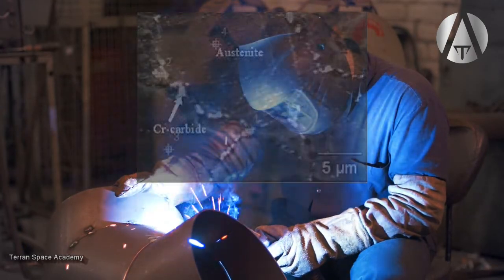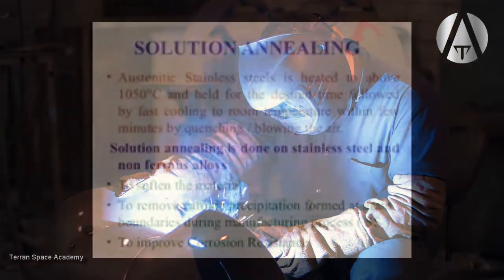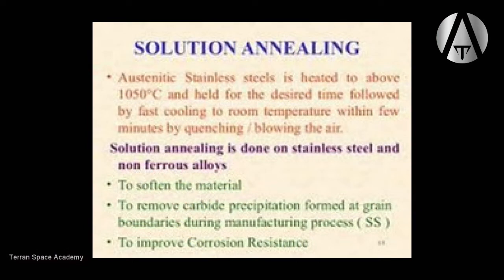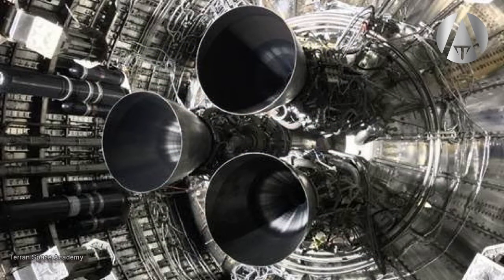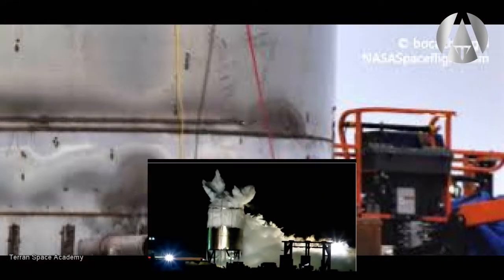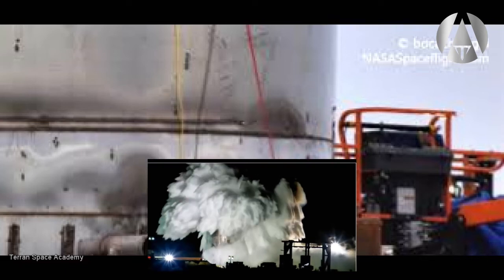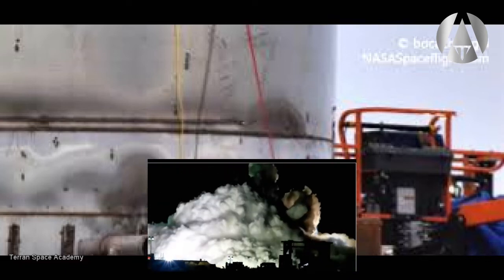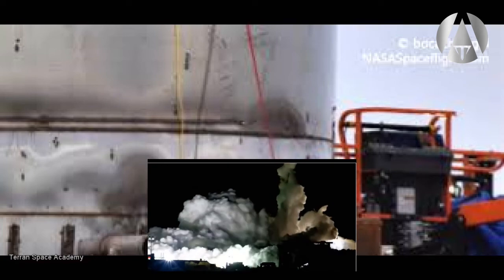What is the solution? SpaceX uses an annealing process to increase the corrosion resistance of the welded areas and adds reinforcing strips in high-stress areas. 301 steel is only about 60% as strong in shear as in tension, so weld points between barrel sections are some of the first to fail under pressure testing. SpaceX has started using two parallel welds to strengthen this area.